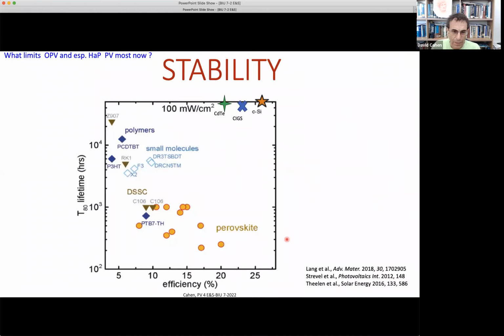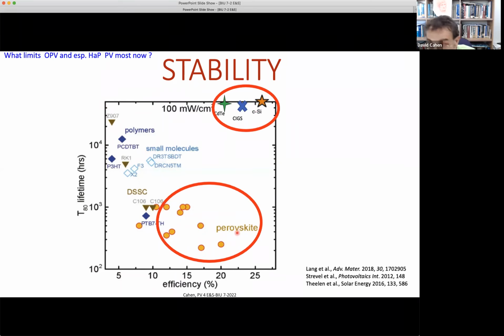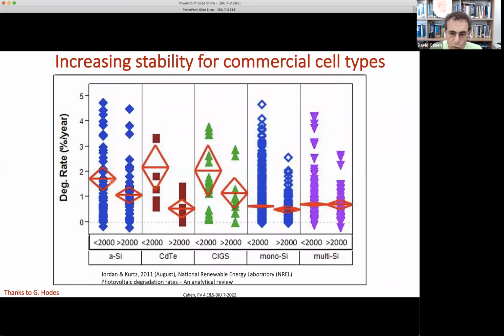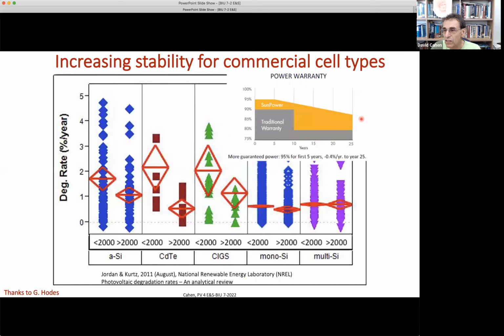Stability. So here are the perovskites. These were considered unstable, telluride and CIGS. At the moment, at high efficiencies, they are as stable as silicon. So the perovskites have to work on the stability. And this is what was done with commercial cells, and you get an idea of the degradation rate per year. There is degradation, but they are guaranteed for 25 years, sometimes 30 years.